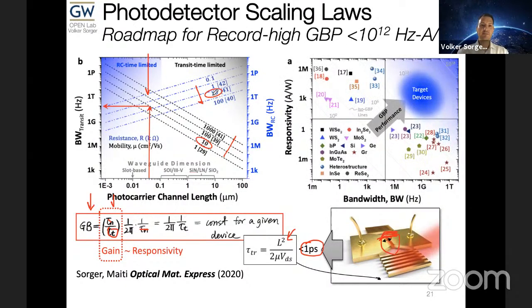We can map this out in detail now. This is showing the transit time limited and RC limited photocarrier speed as a function of channel length, meaning source drain distance. Notice each time you're limited either by RC or transit, for various mobilities and for various resistances. And here's a very interesting regime. With a very modest resistance and mobility, I put it on the right here explicitly, you can actually get up to 100 gigahertz fast devices if you make the channel length very narrow, on the order of tens of nanometers.